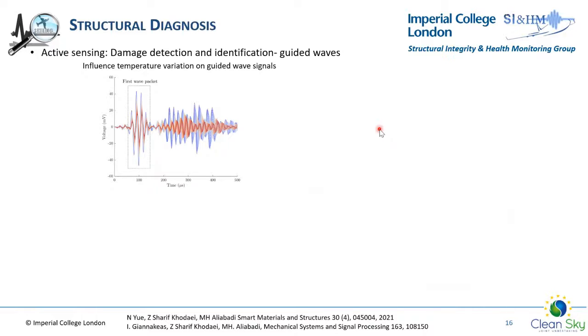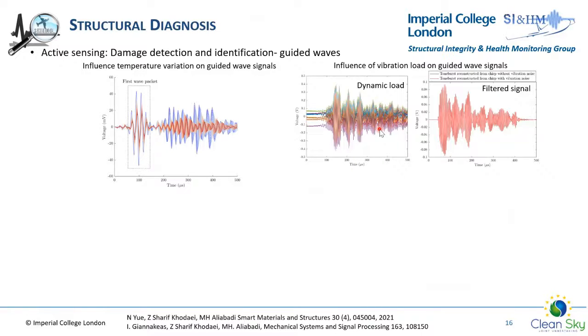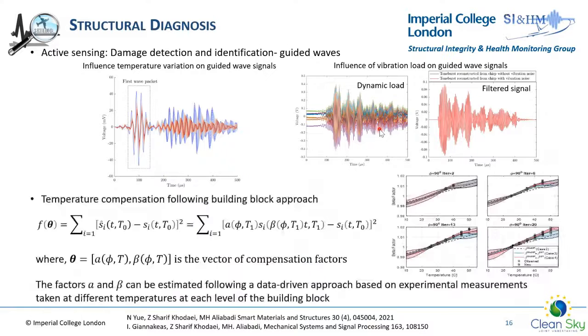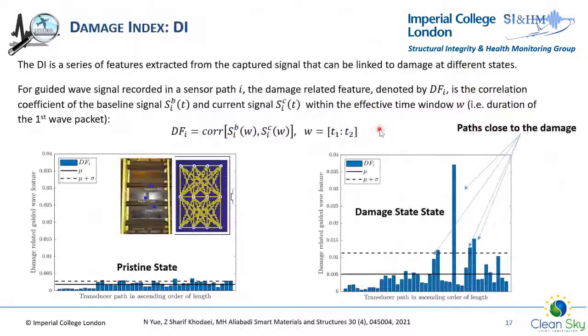reliability of the detection. So really, just very quickly about the effect of temperature and vibration on the signals. You can see an example of how signal is affected by temperature changes and also vibration. So it's very important to be able to compensate for it. What we have done is, again, following building block approach, we developed compensation algorithms for temperature at coupon level. And as we go up the scale, we have updated it and verified and validated it for different scales of the test.